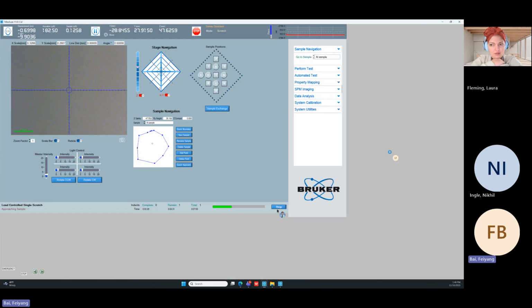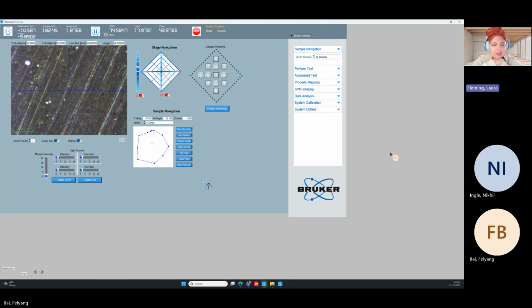Well, the probe is almost touching it. It is not. It will take a very long time at this rate. It looks like it by eye, but from a nanometer level perspective, it's going very slow and it still has quite a ways to go. Should I wait for it to stop and then quick approach? Yes, we should wait till it gets back to the optical position, because quick approaches can only ever be performed from optics. Okay, now go ahead and do a quick approach here.